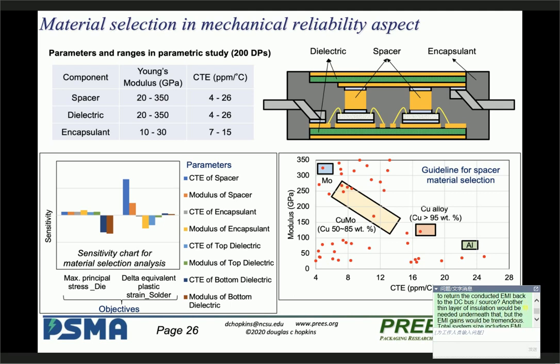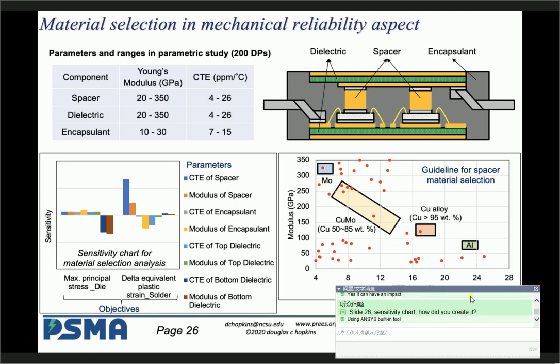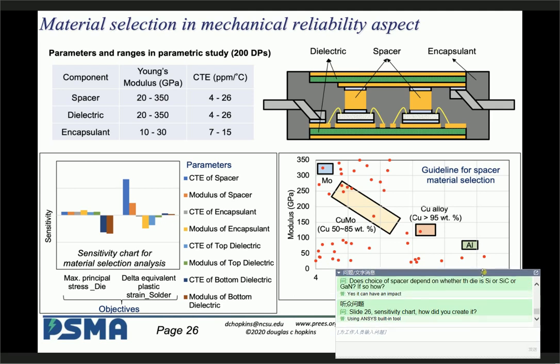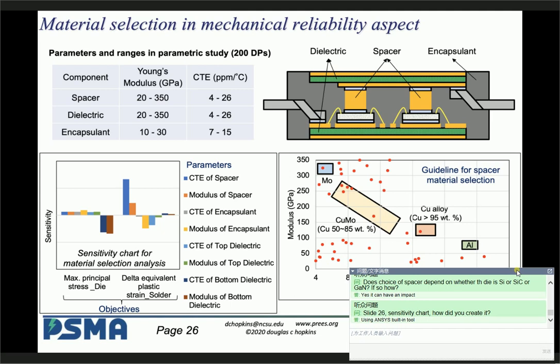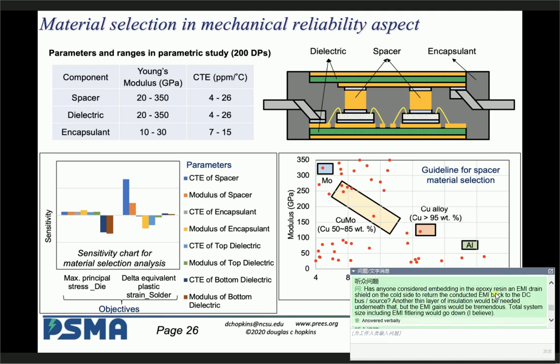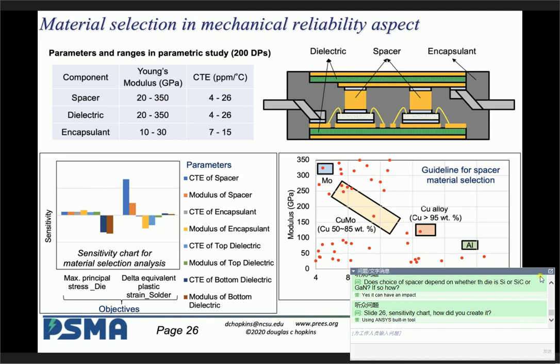Okay, thank you. Next question: does the manufacturer of the epoxy control variance well to guarantee a low partial discharge? If the oxide particles are not well distributed and size controlled, partial discharge in the epoxy will be higher in certain areas, increasing failure rate. It is a good question. The data was provided by our manufacturer, but yes, we need to characterize it ourselves and qualify it under different thickness and different temperature. Those experiments are underway. We need to do that, but we haven't done that yet.